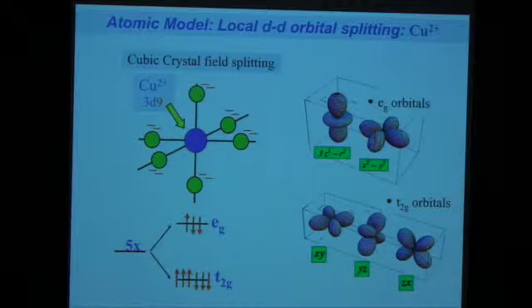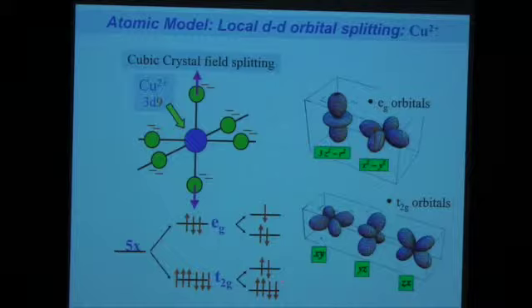Actually, if you distort this octahedron, or as in experiment, it is distorted in lanthanum 2 copper 04, these apical oxygens are moved away from the copper. This will result in a splitting, actually, of these t2g levels. These two will split into an orbital doublet and orbital singlet, and these eg's will also split, and that causes the 3z² minus r² to be filled here, and the hole to be in the x² minus y².